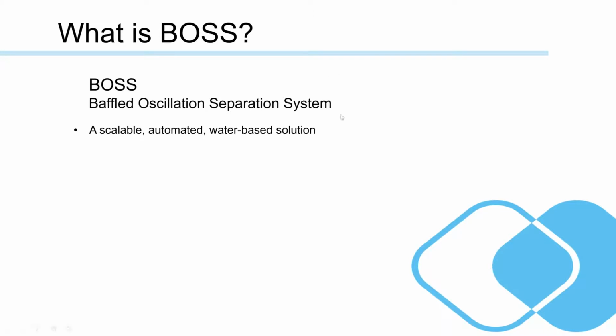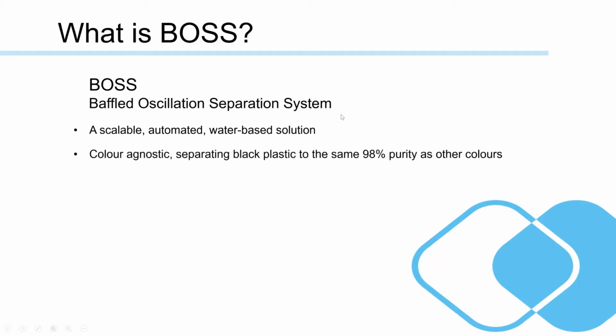So what is BOSS? BOSS really is a scalable, automated, water-based solution. Traditional sorting technologies that can achieve the same purity as BOSS typically use opticals or electrostatic or similar separation technologies, but this has a limitation in that if you cannot scan it or the electrostatics aren't favorable, you cannot separate it. Our system works using only water, which means that we can separate all polymers based upon their apparent density, irrespective of their cleanliness, irrespective of their color.